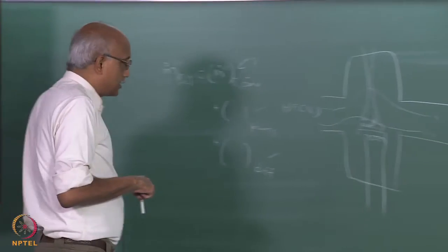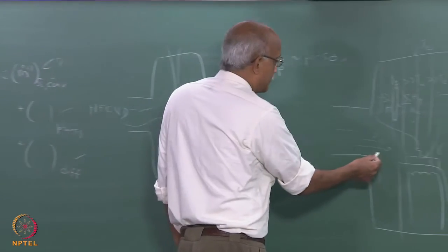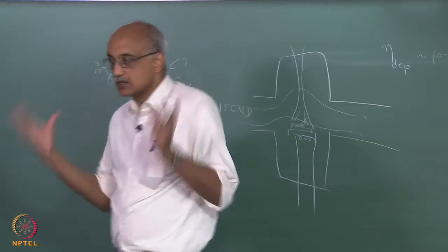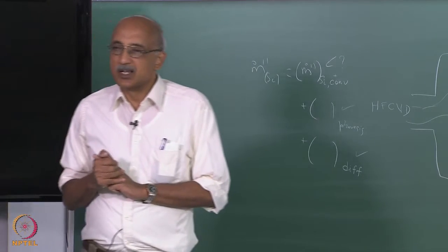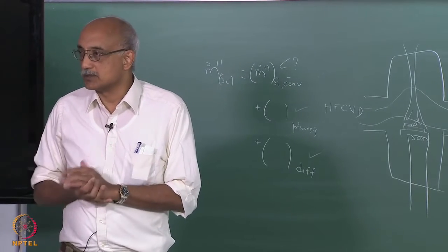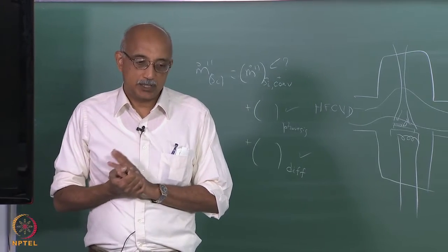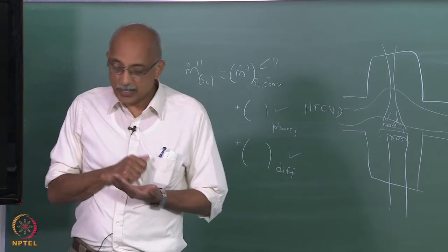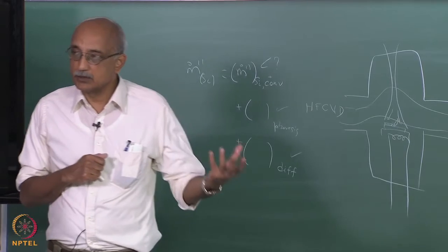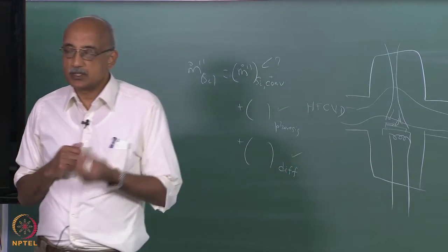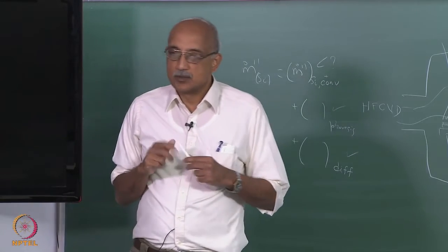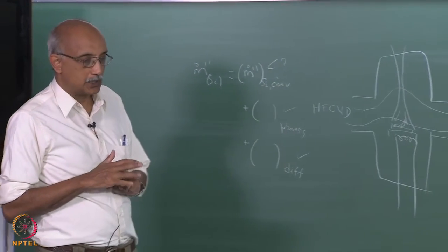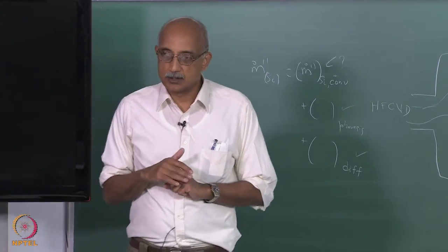And the way that a hot wire CVD reactor is set up, when you have a fairly intense source of heat at one location and the rest of the reactor is being driven at much lower temperatures, it is not easy to achieve uniformity of temperature. So, that can also be a negative factor in use of a hot wire CVD system. Your rates of deposition can be quite high because of the high utilization efficiency, but the uniformity is something that you have to keep your eye on, because it is quite easy for that to be adversely impacted because of the way that this type of CVD reactor is designed.